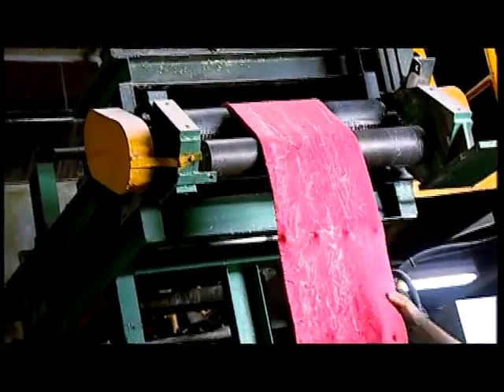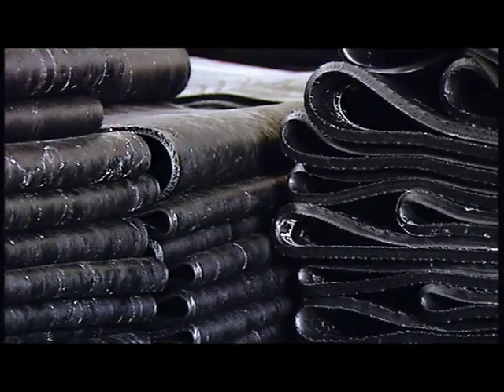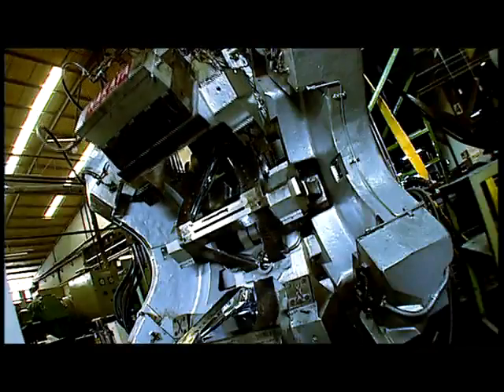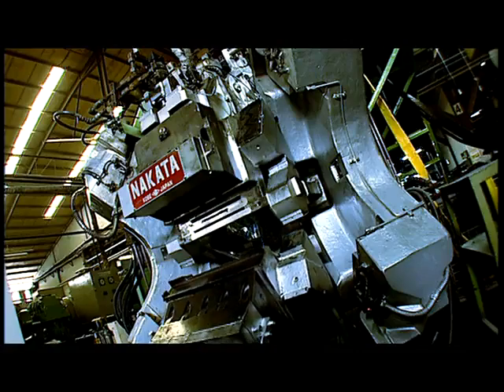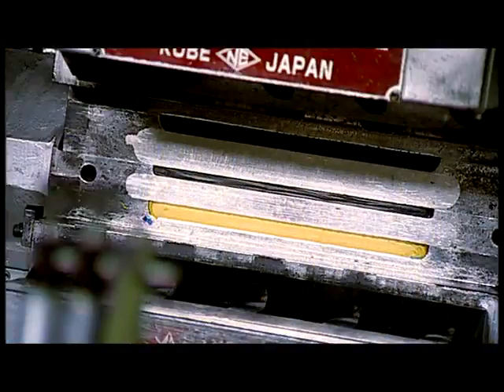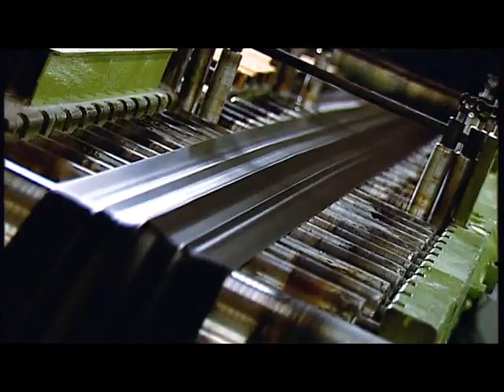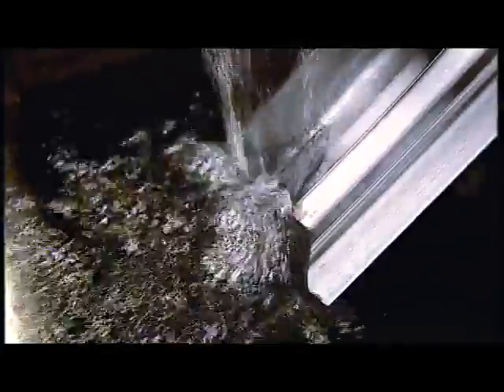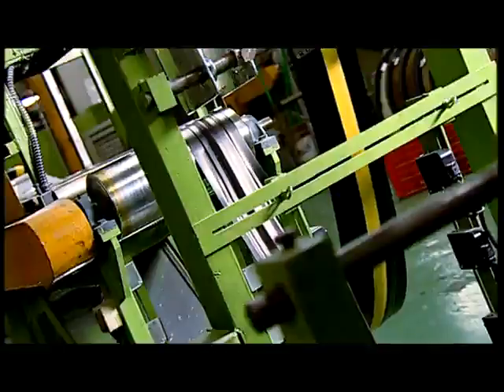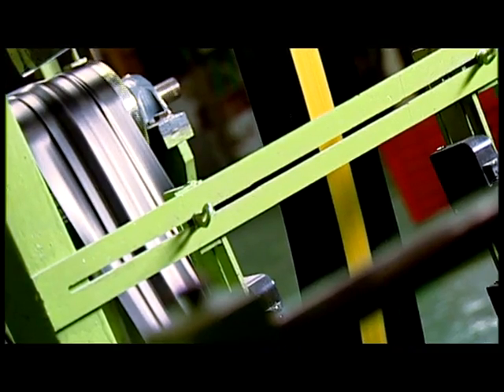The base mixes are rolled out into thick slabs called skins, and temporarily stored before subsequent processing. The extruder combines different rubber mixtures under enormous pressure. A triplex extruder can combine three rubber mixtures — for example, center tread, shoulders and sidewalls. A unique endless strip is produced for each kind of tire, cooled, checked for regular weight, and laid up in rolls.